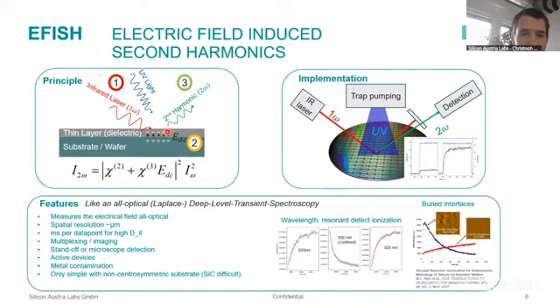When you have this static electric field, as this equation shows, it acts as a second order nonlinearity in disguise, generating the frequency doubled light, which you then detect. The amount of frequency doubled light tells you how much electric field was there, and this can tell you something about the defect situation at the interface.